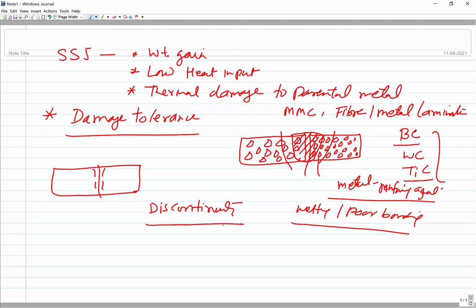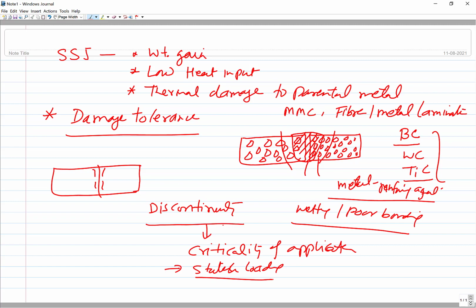Now, what kind of discontinuity, what size of discontinuity can be tolerated has to be identified, and that to a great extent depends on the criticality of the application. Like if there is a discontinuity in a joint which is subjected to static loading, simple tensile or compressive load, probably the discontinuities may not be that damaging. Why? Because there is enough time for localized yielding in the vicinity of the discontinuity to reduce its severity. But that is not the case in high strain rate loading conditions like fatigue or impact. In those cases, we will see the discontinuities very adversely affect the performance.